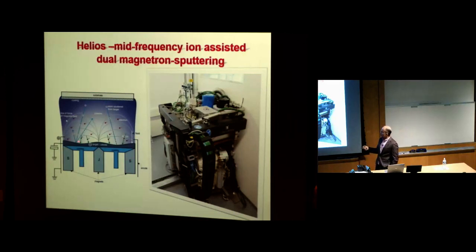Actually, the target for this particular machine should be metal or semiconductor, because we need a conductive material, otherwise all these things will not work. And our plasma consists of oxygen. It means when we produce layers with this machine, we produce either a pure metal coating or an oxide coating. For example, with this particular machine, we cannot produce fluoride coating or some other material which does not include oxygen.